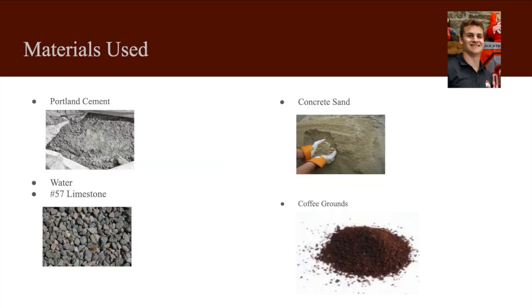In order to test this, we performed a slump test and compression test on three different sample mixtures. One of the samples, being the control sample, contained Portland cement, water, number 57 limestone and fine concrete sand. The other samples were similar except the fine aggregate consists of different ratios of the fine sand aggregate and the spent coffee grounds. One sample contained 85% sand and 15% coffee grounds, and the other was an even 50-50 split of the two.